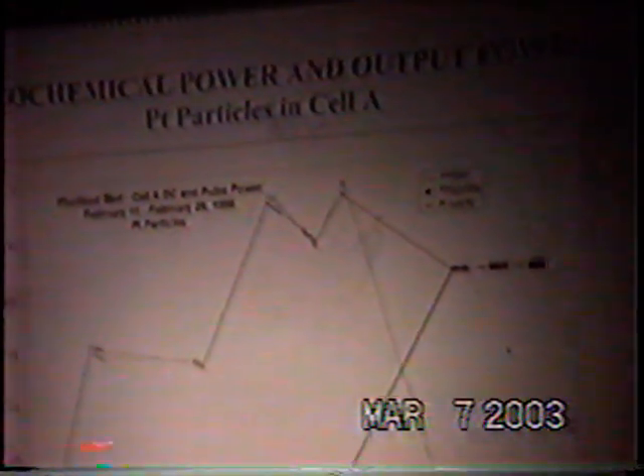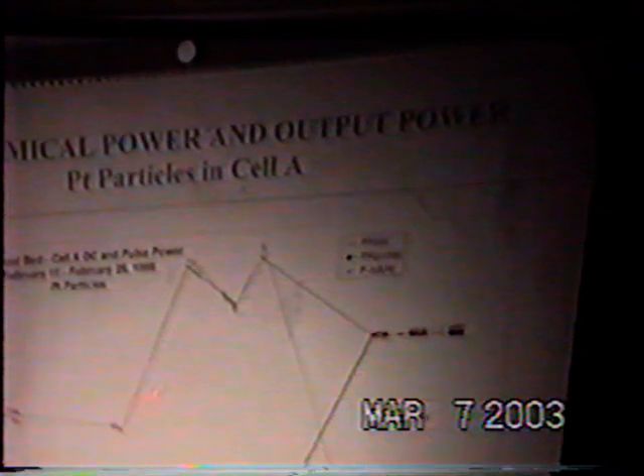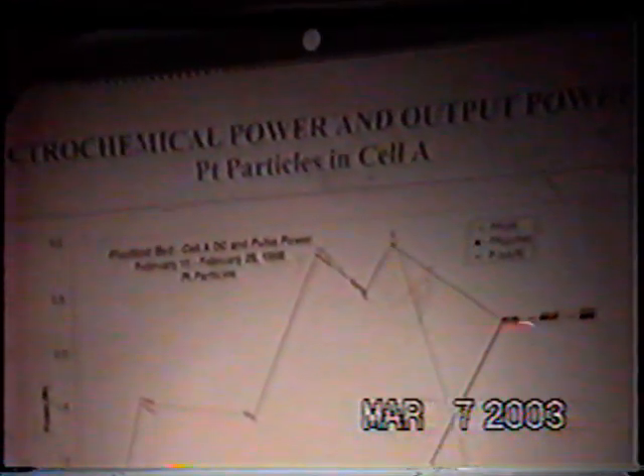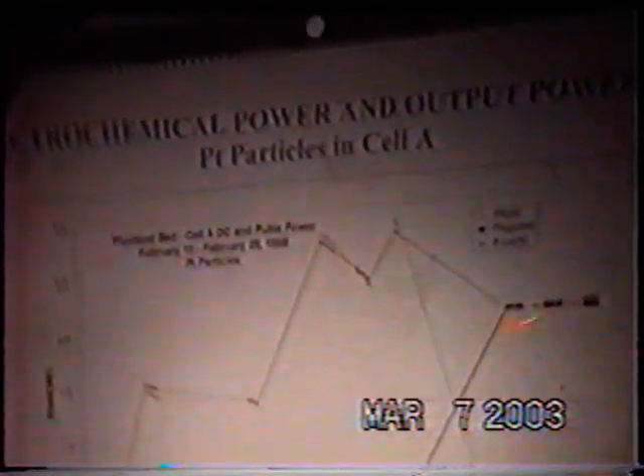This shows the effect with platinum particles. The red is the power out, and the other is the power in. This was direct current, and then we switched to pulse current. Most of the experiment was this regular direct current, and this is pulse current. We can see, within experimental error, the power in and the power out are pretty close to the same.